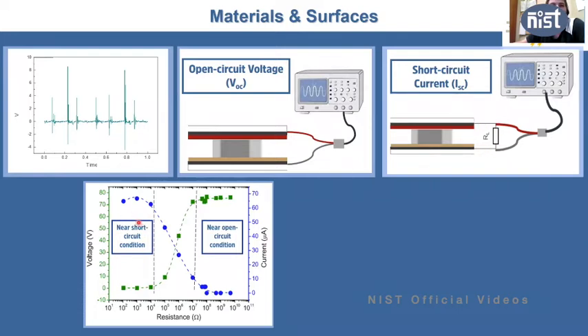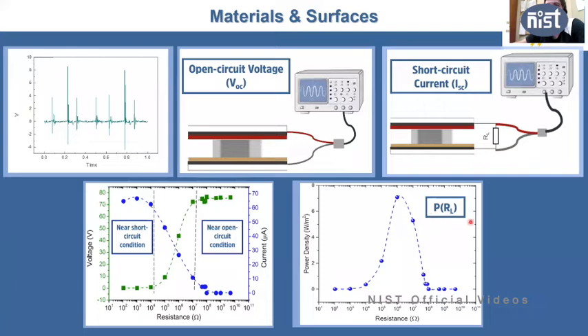And you get the near short condition, where you have a very high current and a very low voltage. You have the open circuit condition, where you have a very high voltage and a very low current. And you have a transition between the two, where the current goes from high to zero and the voltage goes from zero to high. Multiplying these two quantities, you get the power, okay? And you get the power as a function of the load resistance. Typically, it looks like this. So it has a maximum at a given load resistance, which is the internal impedance of your device. And this is the working point that you want to operate on. And this gives you the maximum power also, which is the effective figure of merit of these generators.